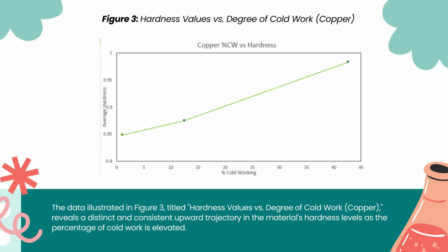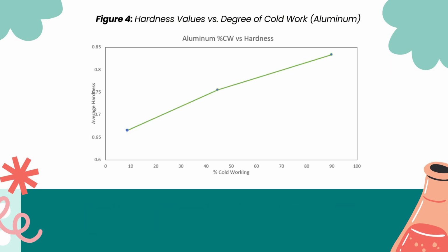Hardness values versus degree of cold work for copper. So as the degree of cold work in the copper increases from 1.11% to 42.66%, hardness rises from 0.848 hardness value to 0.983 hardness value, showing a nearly linear increase in hardness. This trend confirms that greater plastic deformation strengthens copper through strain hardening, improving its resistance to indentation.